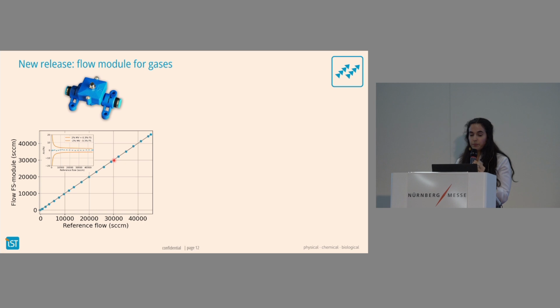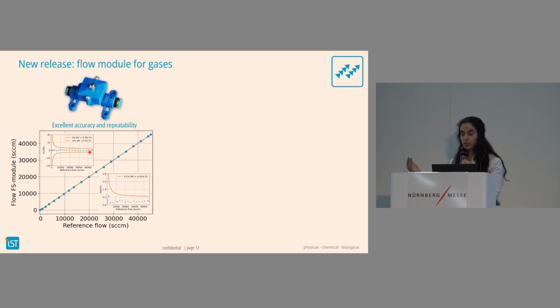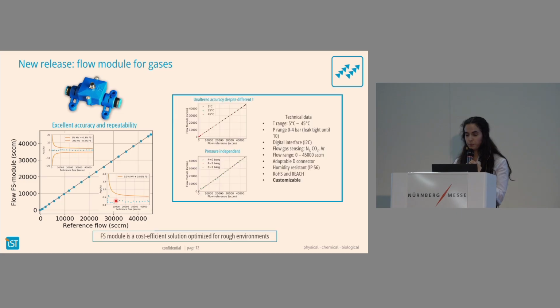on the gray line. The accuracy shows that much better because it's a value that measures the difference between each of these points and the gray line. And you can see that for all the flow range it stays within the limits. And the repeatability, it's a measurement that gives you a feeling of how noisy the signal is. And it also remains quite low, below 0.5% for the whole flow range.